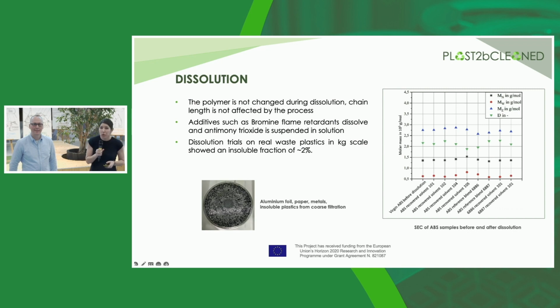In dissolution process, we recovered polymers that have not differ in the chain length compared to the material before the dissolution process. So analysis was made, and no variation in molecular weight was observed. It's important to be noted that dissolution process itself cannot improve the quality of the polymer. So if we already have a degraded polymer stream that enters the process, we can only recover it as such. But important, the dissolution process is not further affecting the quality of the material of the polymer, and it's not degrading this polymer.